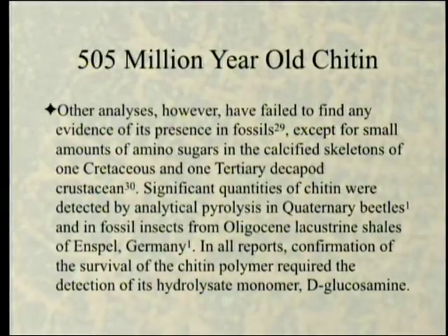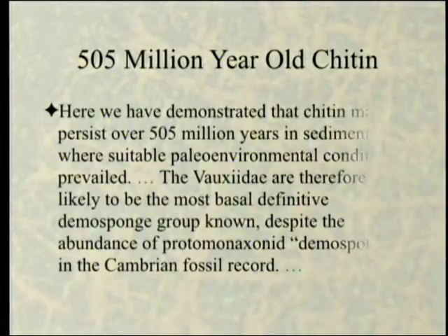Other analyses, however, have failed to find any evidence of its presence in fossils, so some people can't find it, except for small amounts of amino sugars in the calcified skeletons of one Cretaceous and one Tertiary decapod crustacean. And you can look it up in reference 30. Significant quantities of chitin were detected by analytical pyrolysis in Quaternary beetles and in fossil insects from the Oligocene lacustrine shales of Enspel, Germany. So sometimes, with more recent ones, you can find chitin. In all reports, confirmation of the survival of the chitin polymer required the detection of its hydrolyzed monomer, D-glucosamine. So that's how you know for sure.